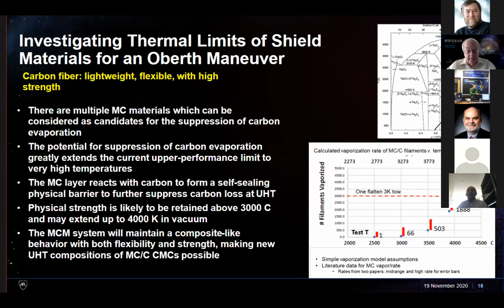And this is a metal carbide over a carbon kind of system, so you have potential for self-healing as carbon comes out from the system. It's reacting with the layer, and it's protecting barriers, so you become less sensitive to defects in the material, because in some sense it's self-healing. So we have some data that shows that this thing works into the 3,000 range, and may be extendable even into the 4,000 range. You're again limited by the materials themselves.